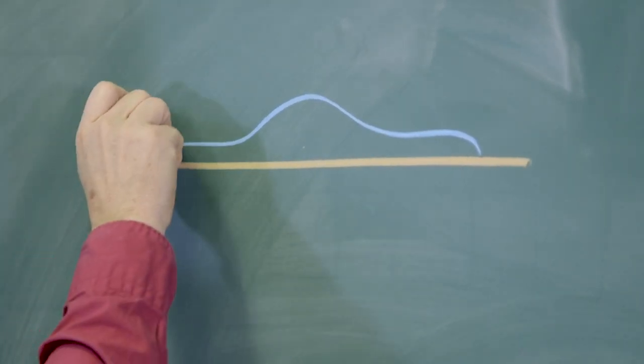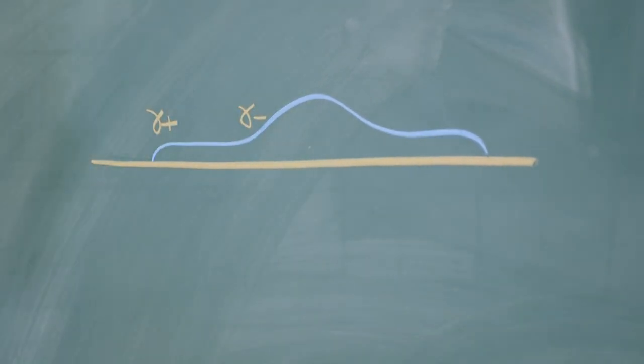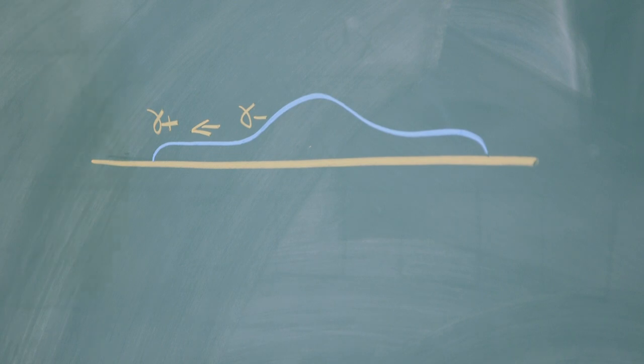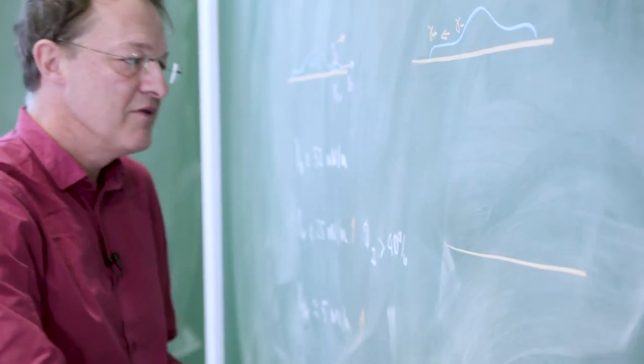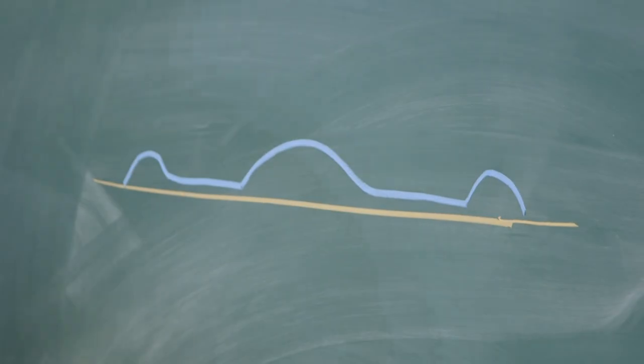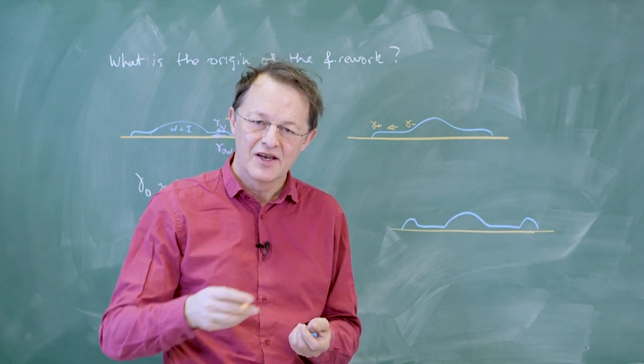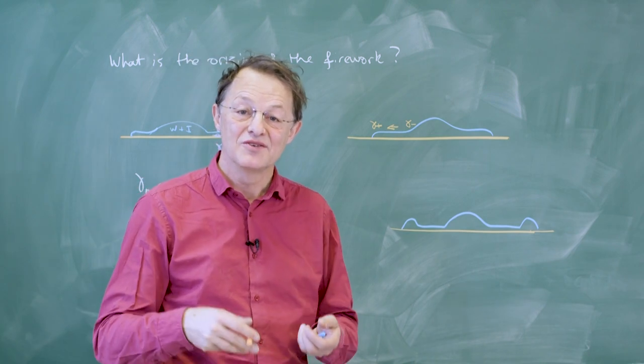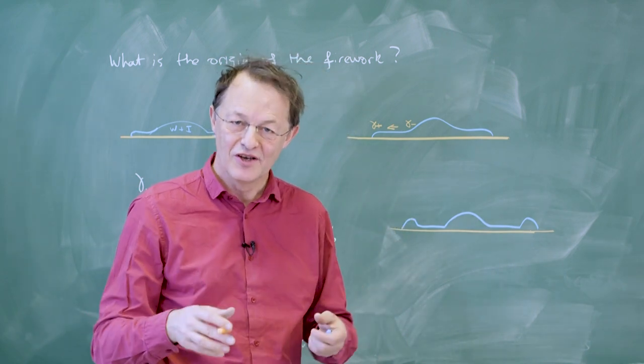And so the situation is quite different. We have the oil, and now the spreading stops at some point. And at this point, we have γ+ here, we have γ- there, because evaporation is less effective inside the drop, and we have a Marangoni flow along the film. As a consequence, slightly later, we have a rim which appears at the edge of this drop, and this rim grows, and because it's a rim, because of its cylindrical geometry, it destabilizes in droplets. And so this is the origin of the firework, the fact that there is a production of little drops at the edge of the main one.